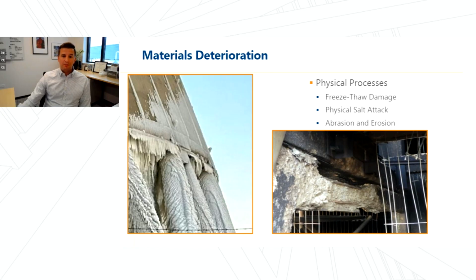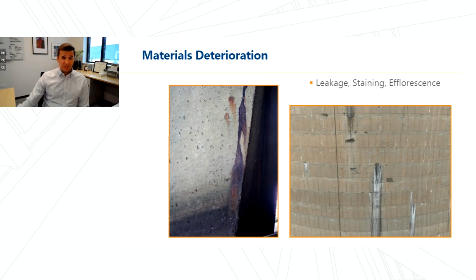And then the last point I want to make here is not really a deterioration mechanism, but when we see things like leaking, staining, and efflorescence, this may be visual evidence of things like a concealed condition, such as corrosion staining in the left-hand image with the crack, or vulnerable areas of the as-built structure. And we see this a lot where we have poor consolidation of construction joints like the cooling tower shell shown here on the right.